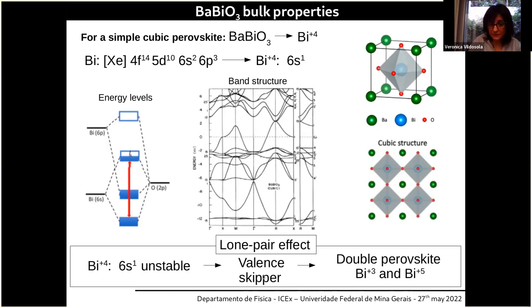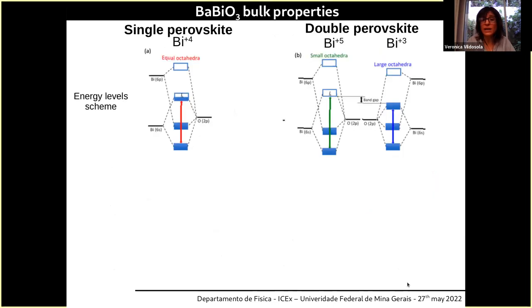But the problem is that bismuth doesn't like this valence state because it is energetically unstable. It would rather be 3+ or 5+. Bismuth is a valence skipper element. Yes? It is called the lone pair effect. So what the system decides to do is to avoid this valence 4+ and double the perovskite and induce what is called a charge order system.